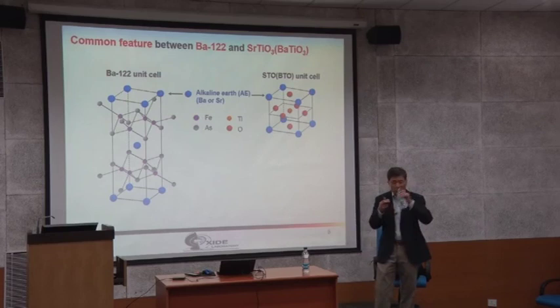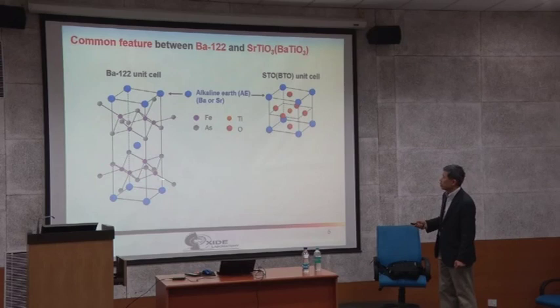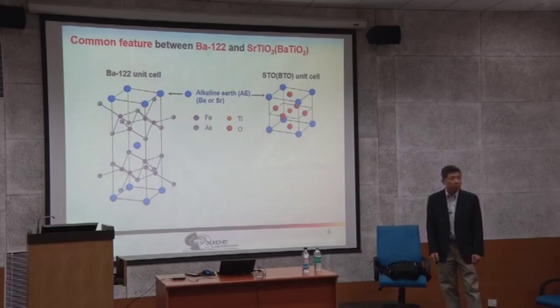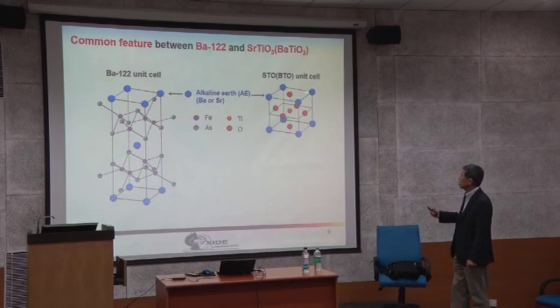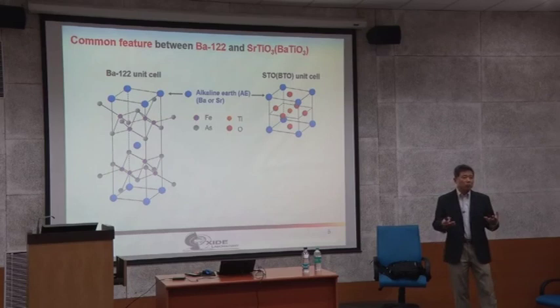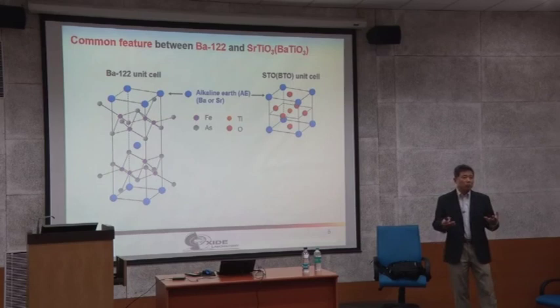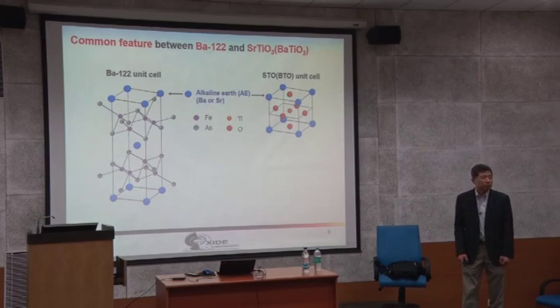To characterize the films, ideally you deposit on an insulating substrate so it doesn't short out your measurement. Looking at the crystal structure carefully: the barium 1-2-2 building blocks are barium and iron arsenide layers stacked alternately. This creates what looks like a tetragonal structure. Compared to the perovskite lattice, it's very similar, and the in-plane lattice parameter is also similar to perovskite structures. So there's a common feature — you might be able to grow this on top of an oxide substrate. The only difference is you have oxygen here.